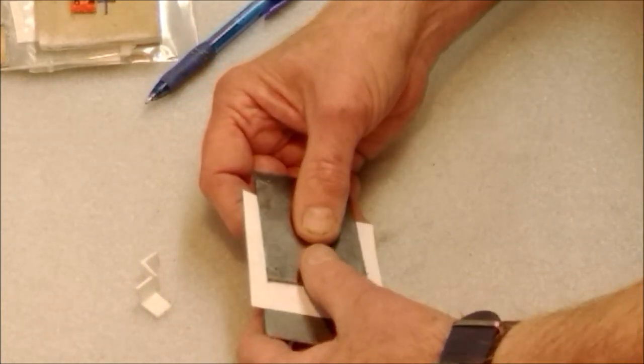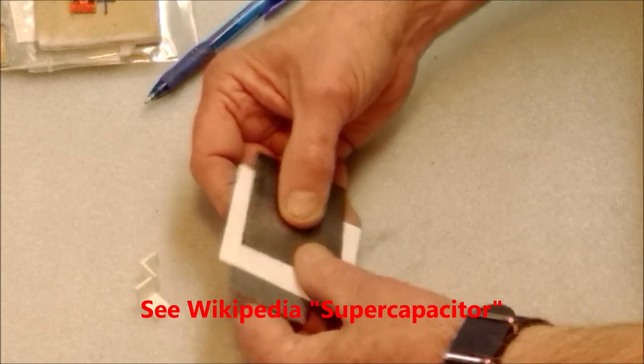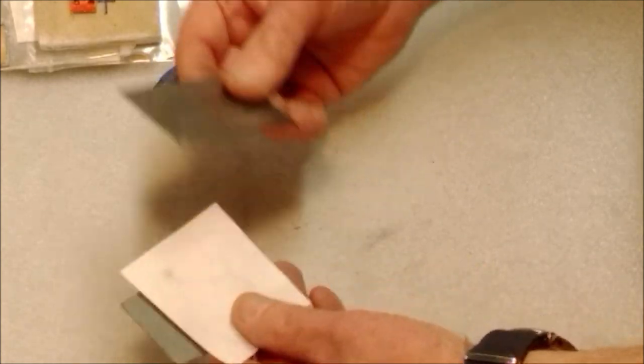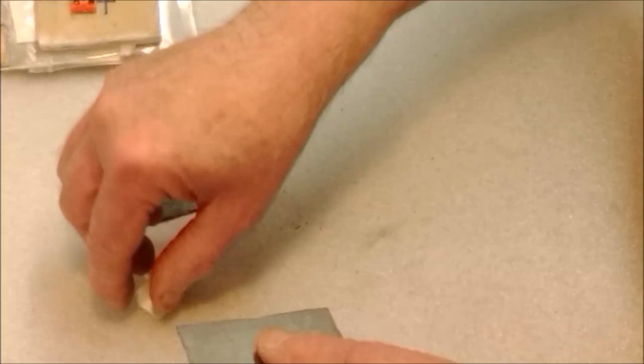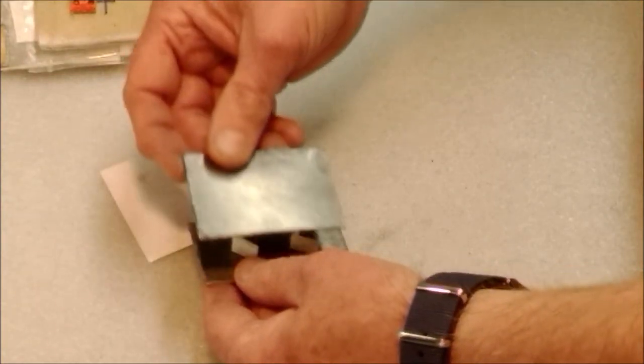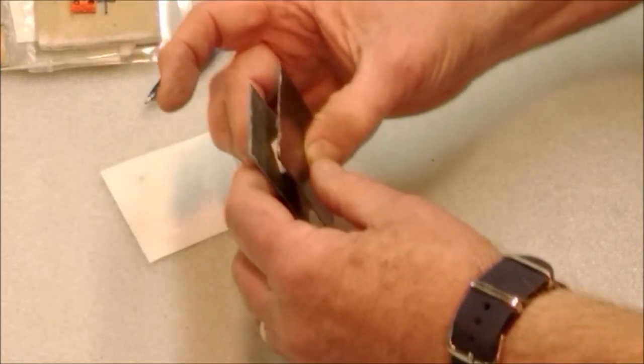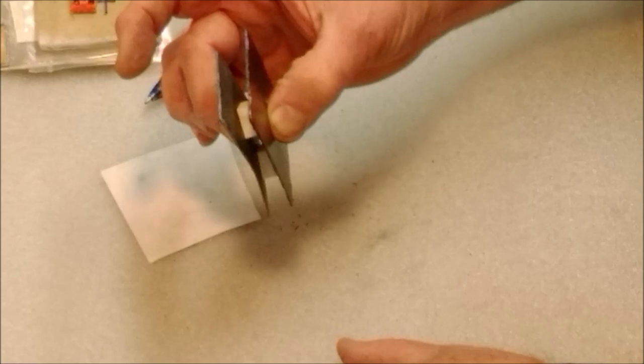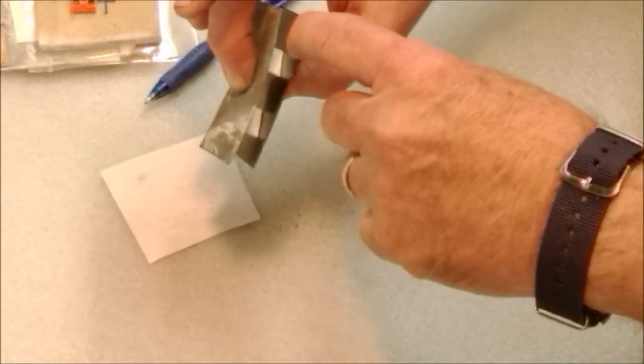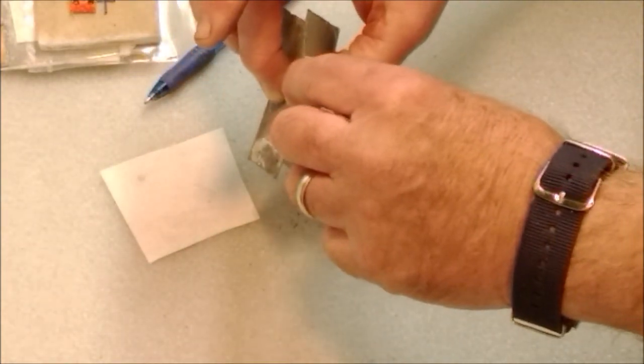To do that, if you remember, there's been a few YouTube videos in the past few months about making graphene, an allotrope of carbon, from a graphite sheet in an electrochemical exfoliation. What that means is you'll take a graphite sheet, space it from a second graphite sheet, take this sandwich, immerse it in an electrolyte, and between the two electrodes here you'll supply a current. After about half a minute, you'll see a little bit of bubbling and a little bit of surface erosion on the graphite foil between the sheets.